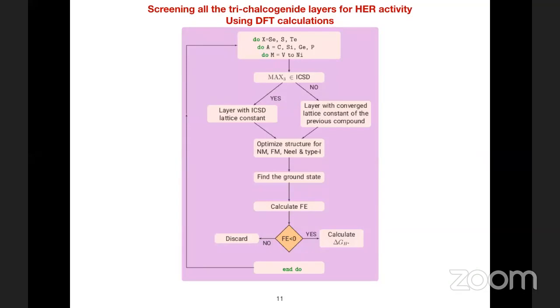What we do here is that we screen all the 72 compounds using standard DFT calculations, which I'm not going to describe. So we loop over the chalcogens, then the central A atoms, then the transition metals, and for each combination, we form these compounds. First, we ask, is it reported in ICSD? If yes, then we take the structure of one layer of these from the ICSD structure. Else, we take as our initial structure the converged structure of the previous compound. In either case, we re-optimize this structure, both lattice constants and the positions of the atoms, in 4 different magnetic states: the non-magnetic, ferromagnetic, Néel antiferromagnetic, and stripe type 1. And then we compare the energies and find out which one is the lowest energy state.